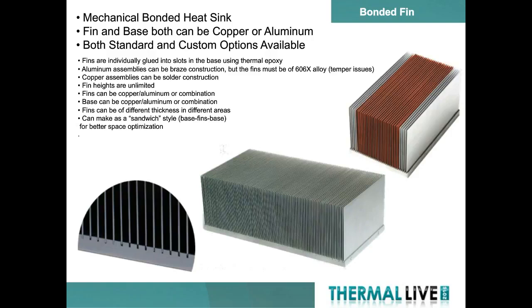One of the other common things that you do with bonded fins is to create what we call sandwich-style bonded fins, with a base on the bottom, a base on the top, and a fin stack. Typically, this allows customers to have a smaller footprint because you can put devices on both the top and the bottom, and either have natural convection or forced airflow through the middle. Also, because the base and the fins are separate pieces, you can mix them back and forth. So you can have a copper base and aluminum fins. Usually you can do this for thermal conductivity or for weight reasons. And a couple of the heat sinks that we've produced in the past for extreme weight solutions actually use graphite fins, which are lighter than aluminum, but have a thermal conductivity equal to or better than copper.